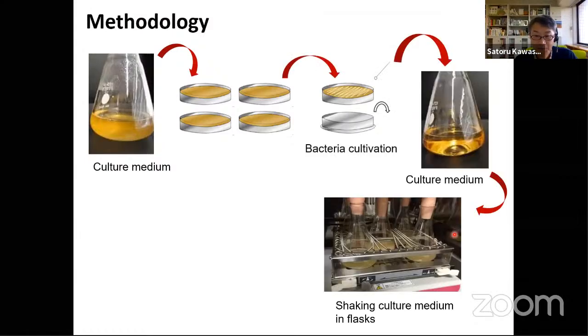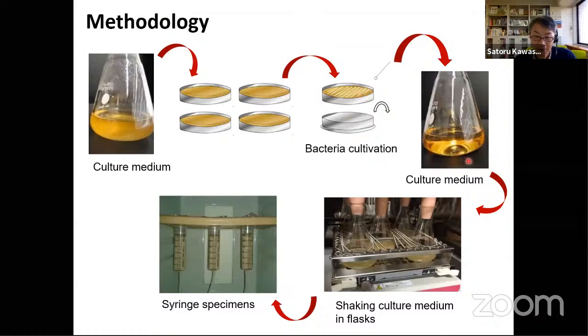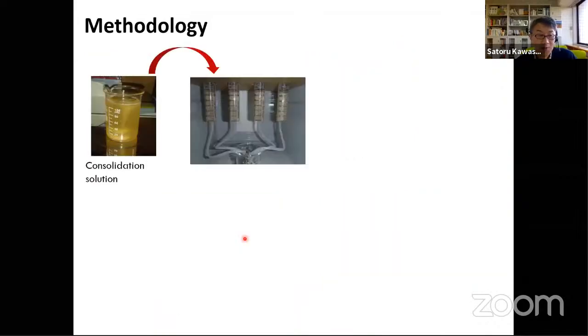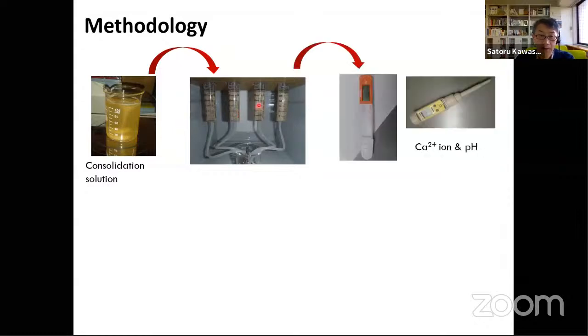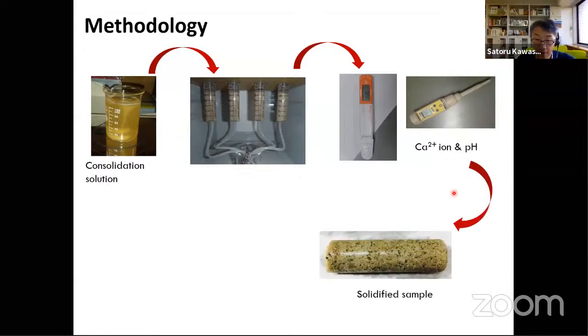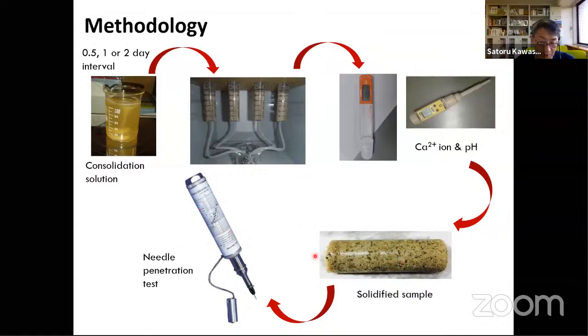The bacterium cultivation methodology is skipped; like this, shaking, then poured from the top. And this one is the methodology. First we prepared a consolidation solution including bacterium. This syringe is filled with coral sand. Then, after collecting outlet solutions, we measured calcium ions and the pH. After conducting the syringe solidification test, we obtained the solidified samples. Then we conducted a needle penetration test in order to evaluate the estimated unconfined compressive strength, the estimated UCS.